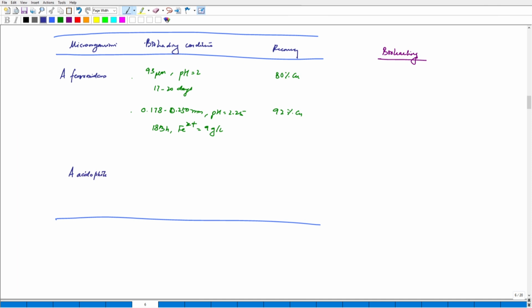And if let us say we have a different microorganism, we have acidophilum, then we can have 60 ml acidophilum supernatant. So this is basically supernatant. And then we have 15 ml H2O2, 60 degrees Celsius, kept for 2.5 hours. This can give us nearly 100% copper. Again, putting up some references here.